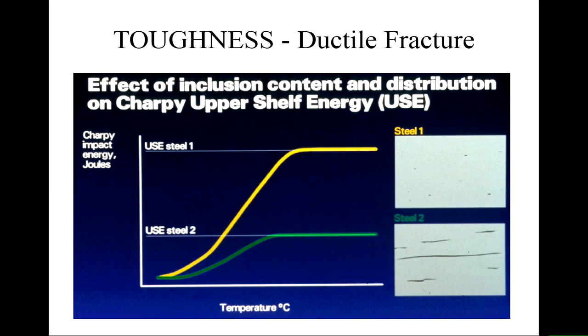Okay, so I gather that Dr. Euler finished the last lecture with some words about ductile fracture. Basically, when you have a steel which is reasonably well prepared, the quality of the steel, which is related to the amount of impurities in the steel, can have a big effect on fracture. And the example that you can see here is a couple of steels with the same basic composition, but one of them has a little bit more sulfur in it than the other one, and it's the one at the bottom that has more sulfur.